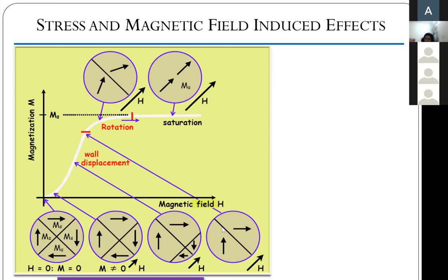Still, one can see that up until this point, increasing the magnetic field is not causing the domains to rotate. There is only domain growth happening until a moderate field value. Then, when I keep on increasing the magnetic field a little bit more, right now only the favorable domains have remained. But if I further increase the magnetic field strength, the domains will start to rotate. They'll keep on rotating until all the domains are fully aligned with the applied magnetic field. And this magnetization strength, Ms, is a constant value for a material.